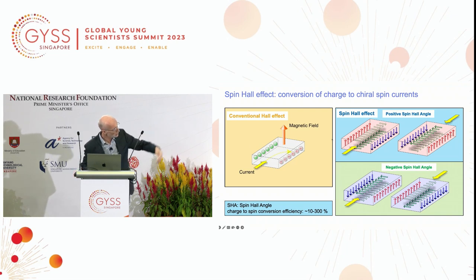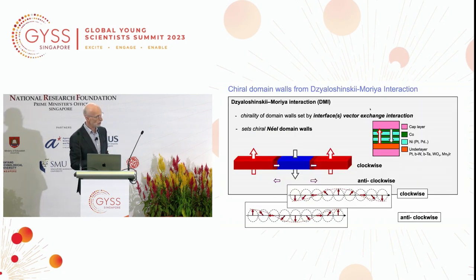So if on the right top, you can see this material, this pink material, let's say it's platinum, we pass this current, yellow, through the material, and you can see these arrows, they correspond to spin polarized electrons that accumulate on all the surfaces in a chiral direction. When you change the direction of the current, the chirality changes. So on the surface, we'll end up with accumulation of spin-polarized electrons, no charge accumulation. And now what happens, we can use that spin-polarized current and pass it into a neighboring magnetic material to create spin-orbit torques. And that is what we demonstrated. And today, the efficiency of converting one electron into a spin-polarized electron exceeds one. Some recent materials we published earlier last year, we demonstrated that every charge electron can generate two or three spin-polarized electrons. That's the first. This is a chiral phenomenon. The chirality of this spin current depends on the material.